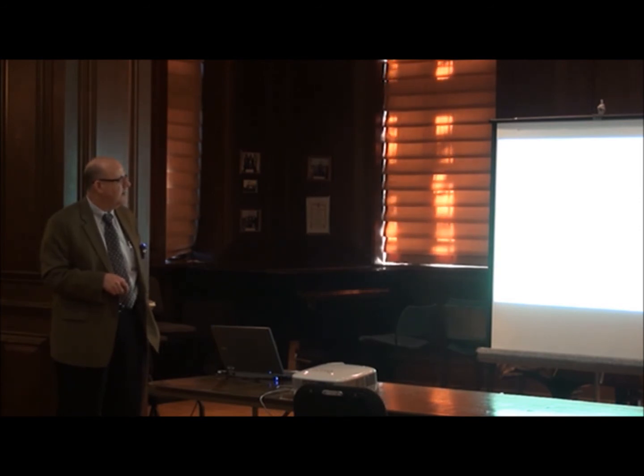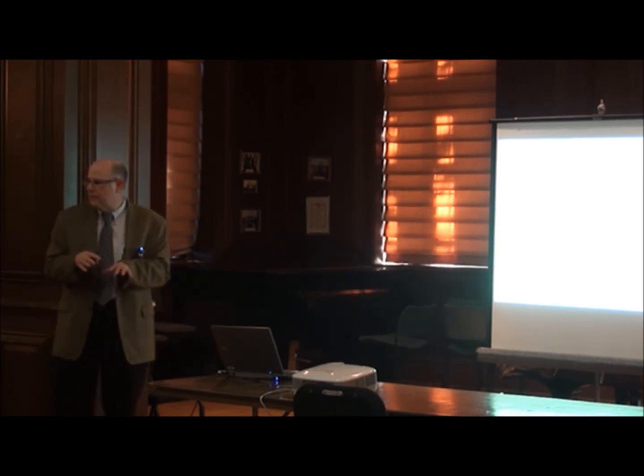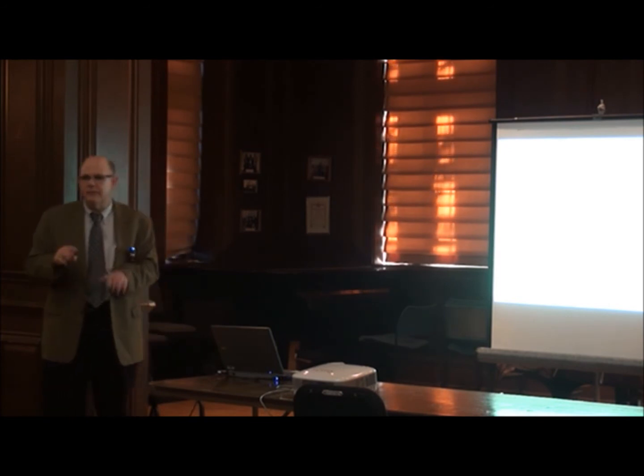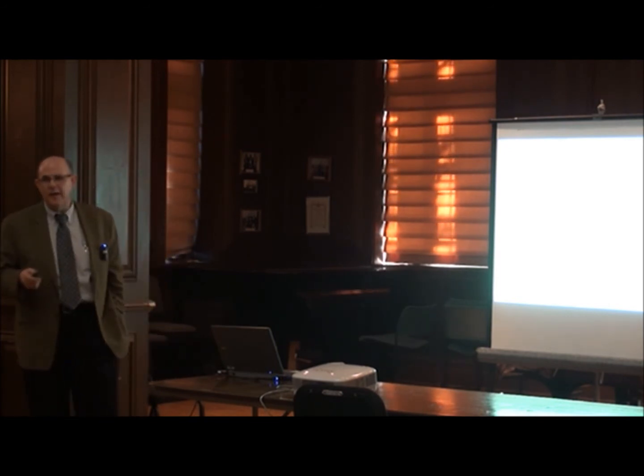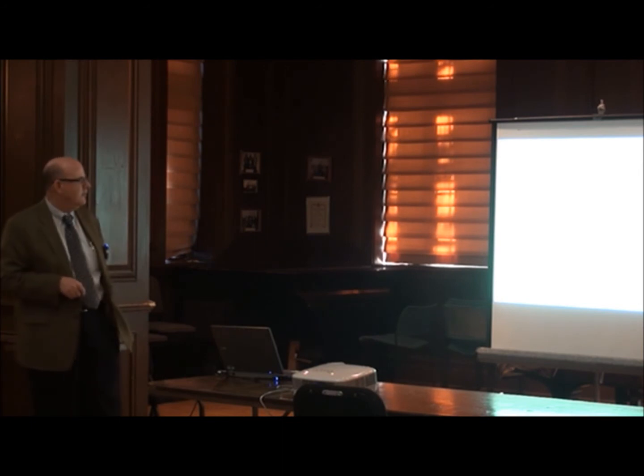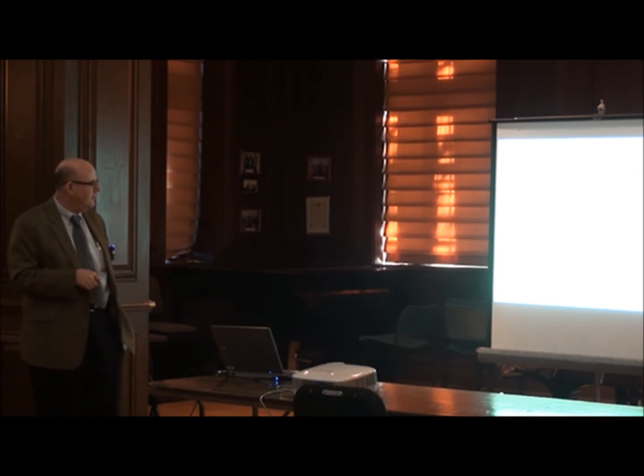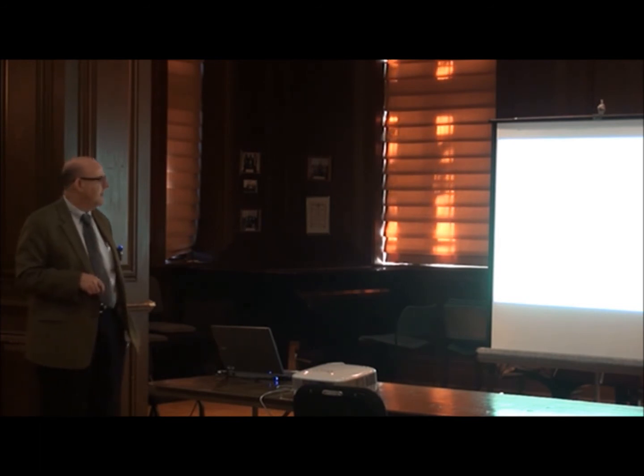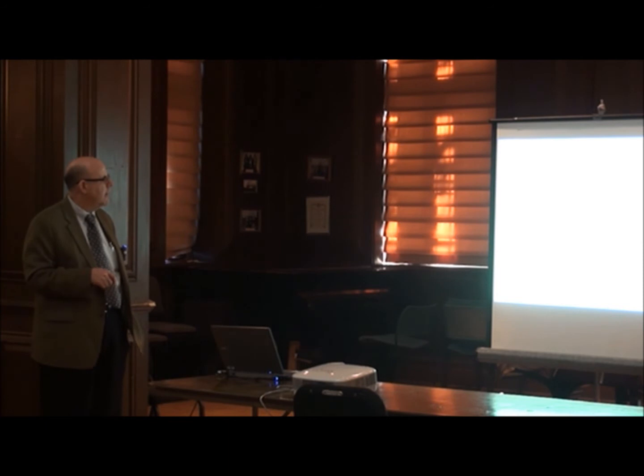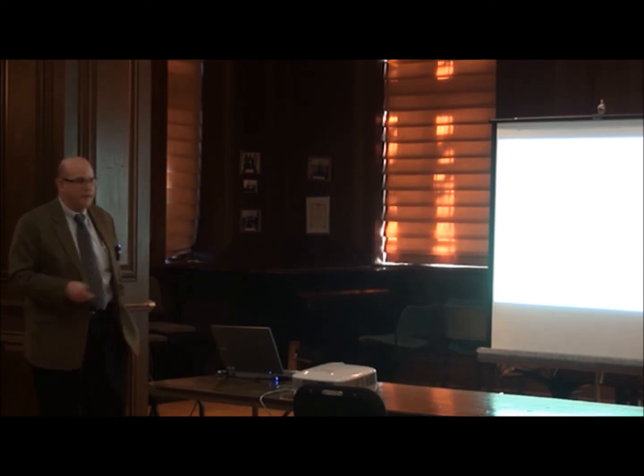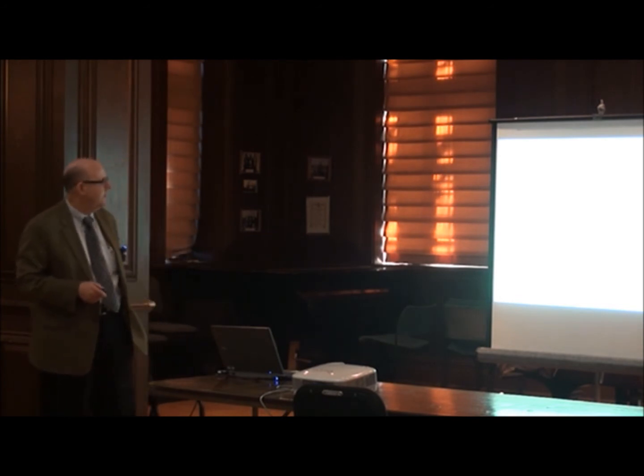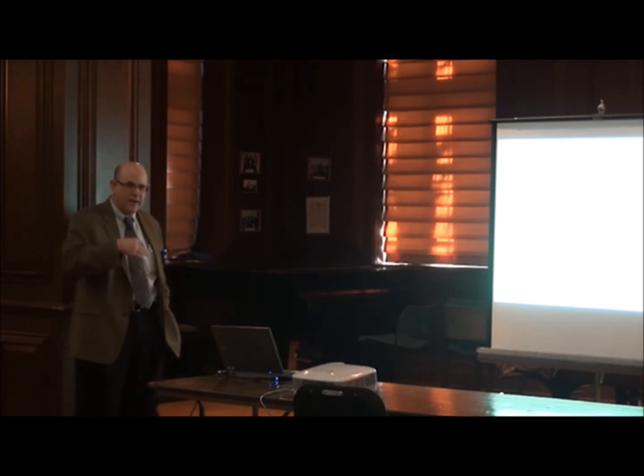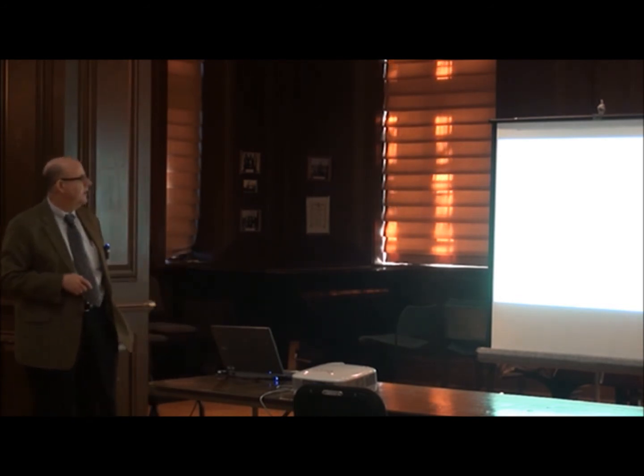If the lambda ratio is real large, then the surface texture doesn't matter too much. If you've got a thick enough film, thick enough relative to the RMS roughness of the two surfaces, certainly the surface texture doesn't matter. As that lambda ratio starts to approach 3, it definitely matters. And as you get to 2 and 1, it's a pretty significant effect. So when you're getting close, 2 or 1, and you have longitudinal roughness, you get a lot of extra flow through that interface. If you have transverse roughness, you kind of get flow being occluded.